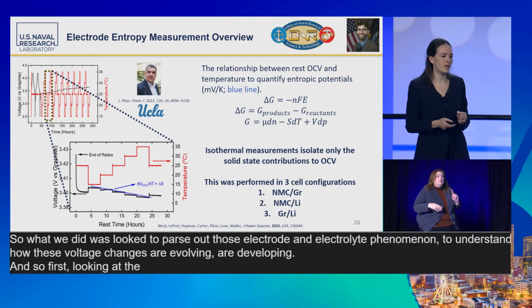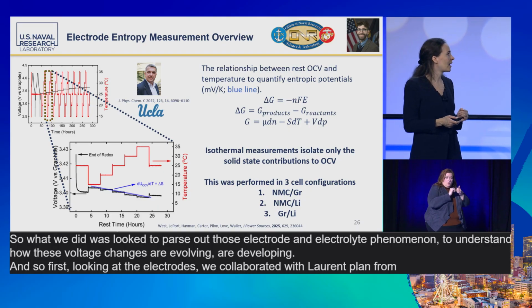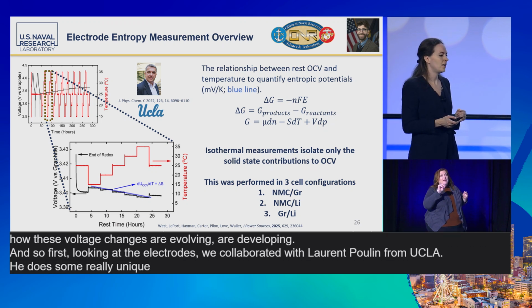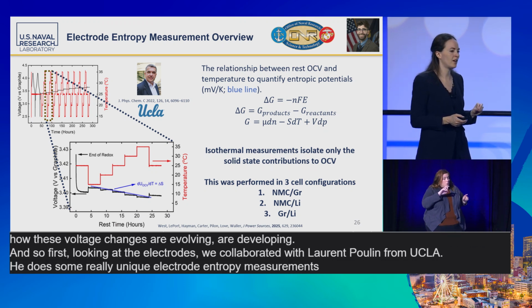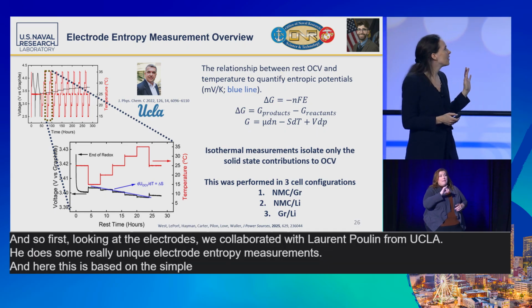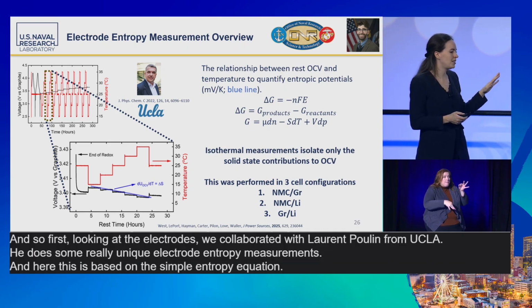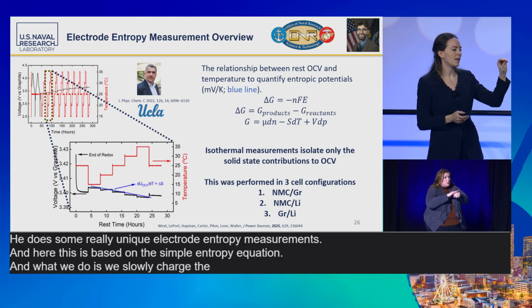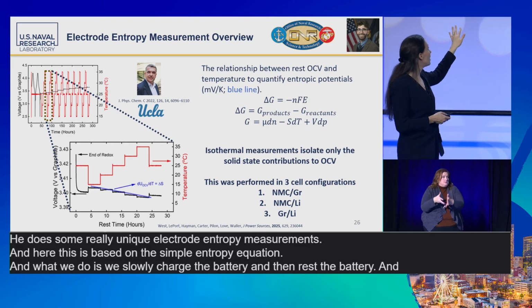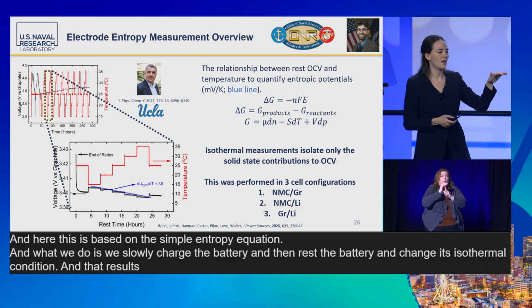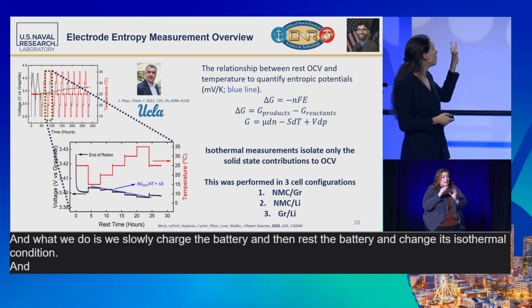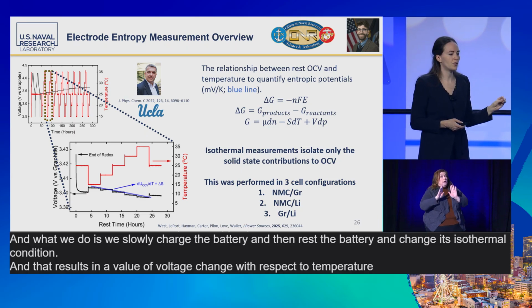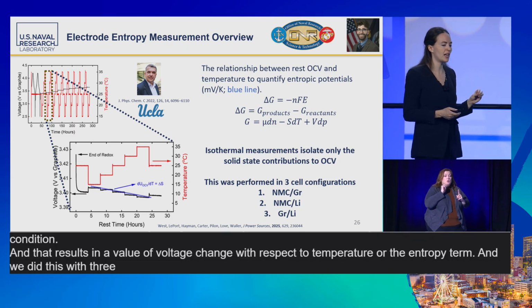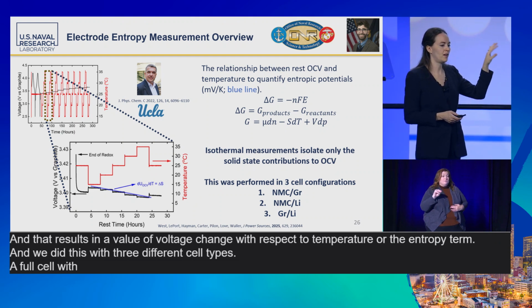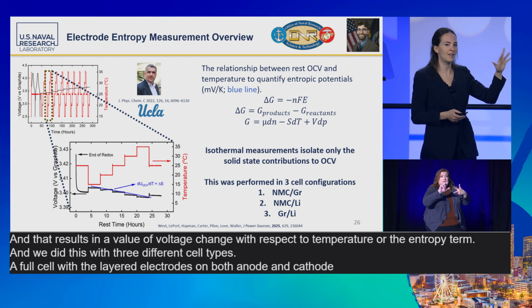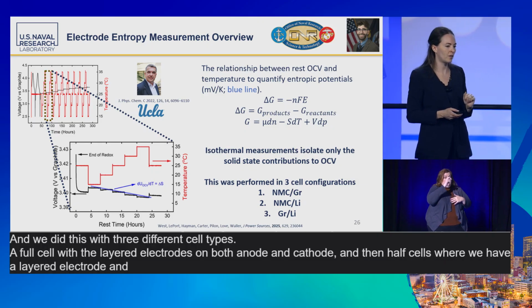And so first, looking at the electrodes, we collaborated with Laurent Poulin from UCLA. He does some really unique electrode entropy measurements. And here, this is based on the simple entropy equation. And what we do is we slowly charge the battery and then rest the battery and change its isothermal condition. And that results in a value of voltage change with respect to temperature, or the entropy term. And we did this with 3 different cell types. A full cell with the layered electrodes on both anode and cathode, and then half cells where we have a layered electrode and a lithium electrode.